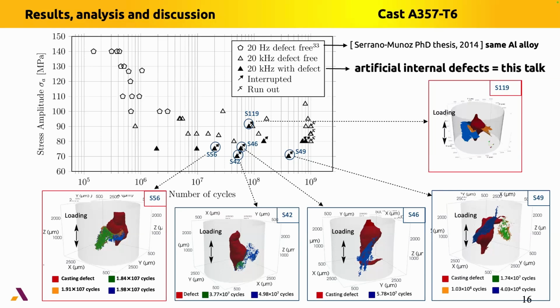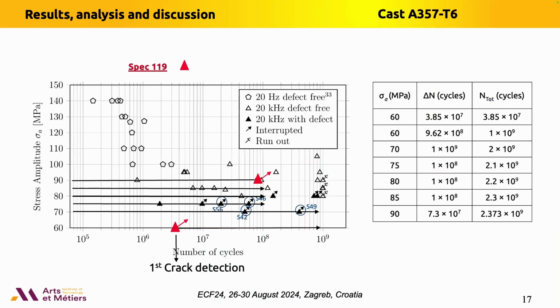I have not enough time to present all of them. So first, the specimen 119. This one is very interesting because it has a very special response that we observe only 2 times, in 2 specimens. On this specimen, we have loaded the specimen at 60 megapascal, and the first crack was detected after approximately 4 times 10 to the 7 cycles. And we apply the testing procedure step by step. So we apply several numbers of cycles and we try to observe the crack propagation. But in fact, after 10 to the 9, we observe no crack propagation. The crack was arrested. So since the time is limited at the synchrotron, we decided to increase a little bit and we load again the specimen at 70 megapascal and we continue the procedure.